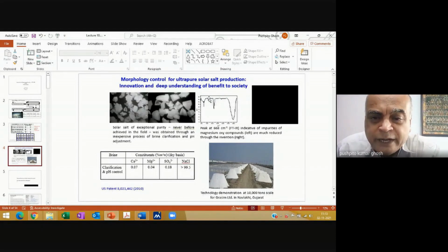And by doing an infrared spectroscopy, this particular peak revealed a lot. What it revealed is that there is a fair amount of what is known as magnesium oxychloride. This particular wavelength is very characteristic of that. And we said, oh, magnesium oxychloride is known as a cementing agent. It somehow likes to bind things up.